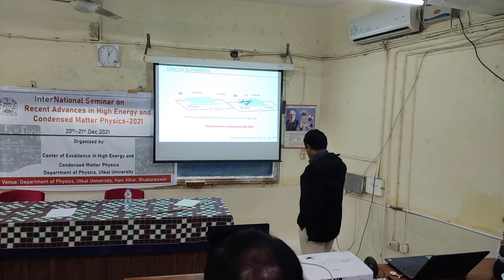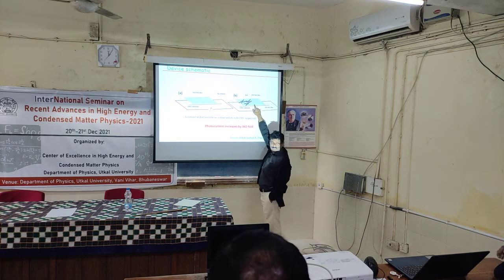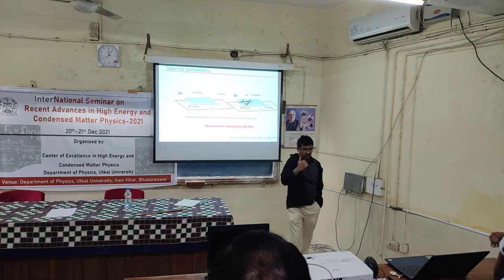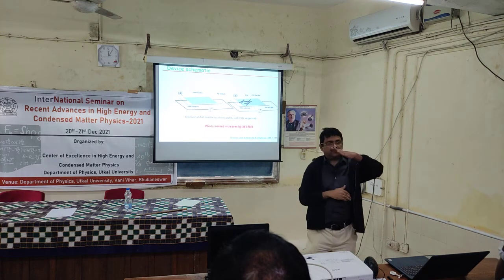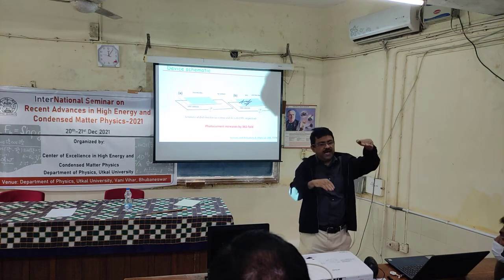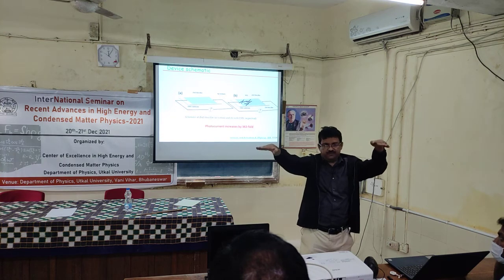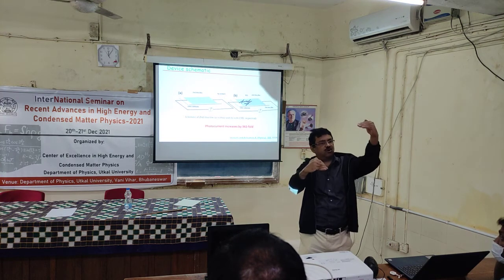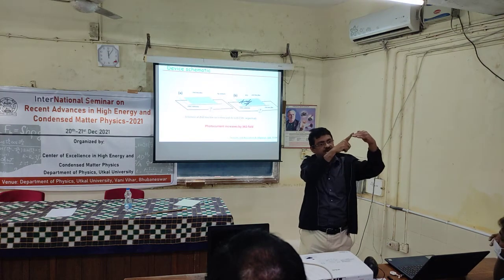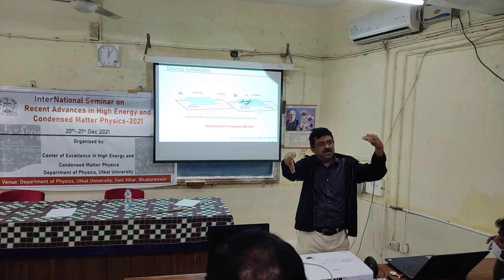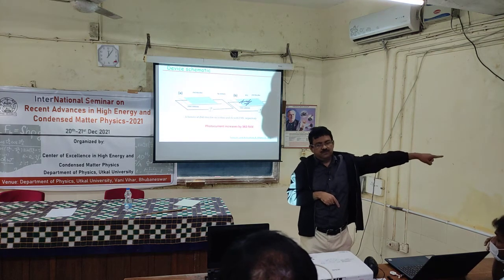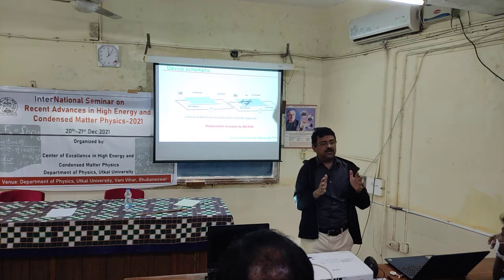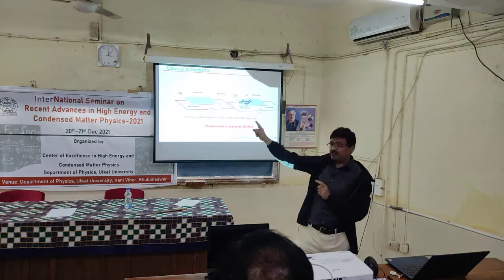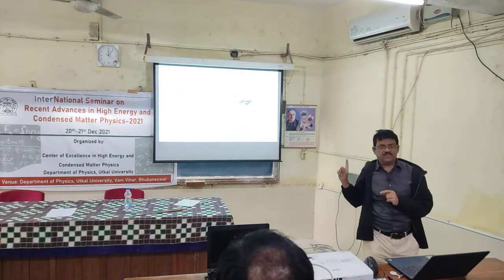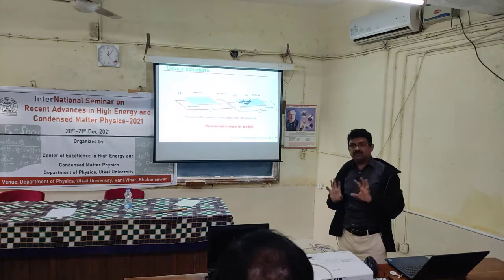How does it happen? You shine UV light, and the zinc oxide generates electron hole pairs. The electrons go to the conduction band of zinc oxide, and the Fermi level of the carbon nanotube is below the conduction band of zinc oxide. So once the electrons get there, they are transferred to the carbon nanotubes, and through the carbon nanotubes they go to the electrodes. So the recombination of the electron hole pairs can be suppressed or avoided by providing another path for the electrons. The concept is very simple.